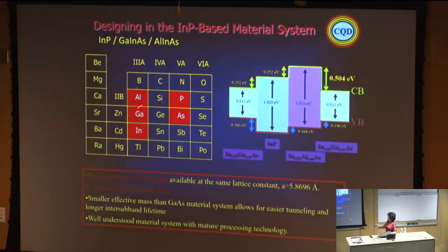I used the III-V semiconductor, especially phosphorus-based indium phosphide, because they were working with gallium indium arsenide and aluminium indium arsenide with MBE. So I developed not only the atomic and gap engineering of this material, so that we can have not only perfect lattice matching to indium phosphide, but also strain balancing to change the gap, especially the discontinuity of the conduction band, while keeping perfect lattice matching.